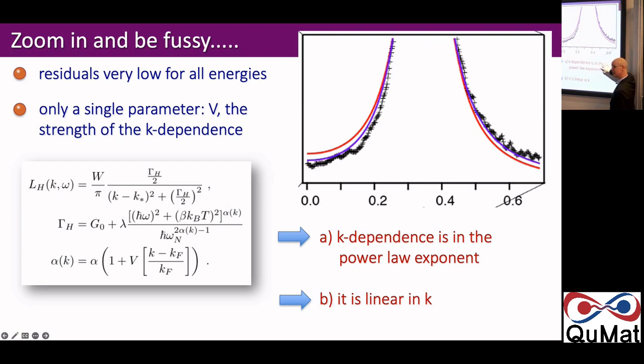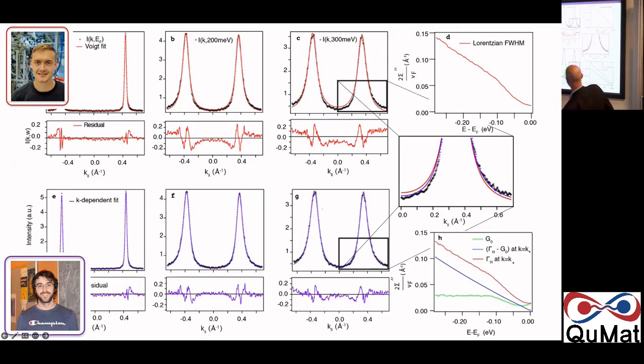So we have a K dependence experimentally shown to be in the power law in these systems, and the K dependence is linear in K away from KF. Okay, so this is the pièce de résistance from these 2 young guys. I just put it on once more: getting data of this quality and getting to a theory which can explain even the minutest details of this data, but without putting in a bunch of banana coefficients that Enea just can tune depending on the weather in Italy. No, this is really based on a pretty locked down theory coming from semi-holography.